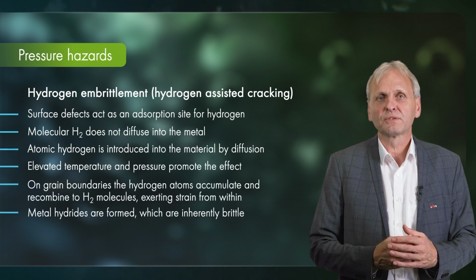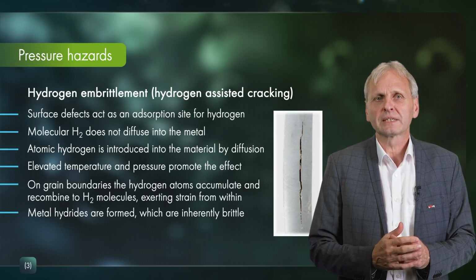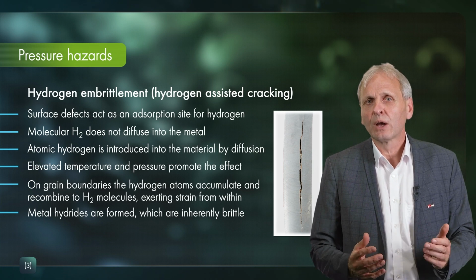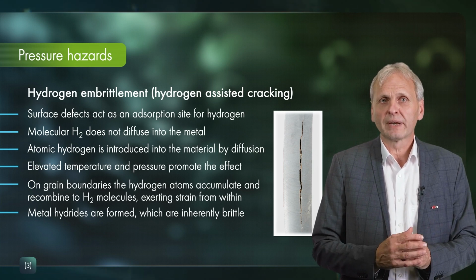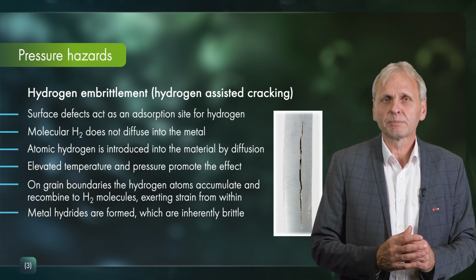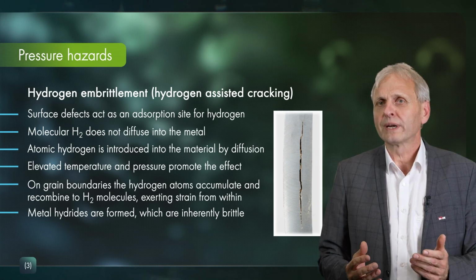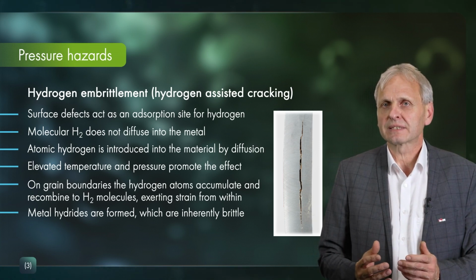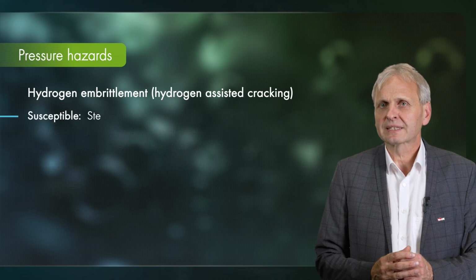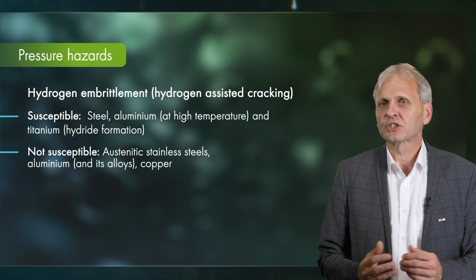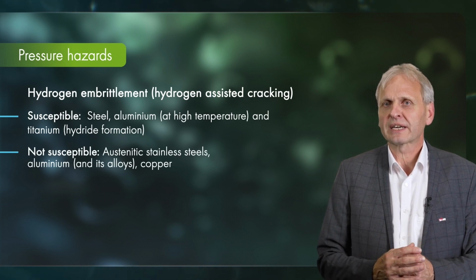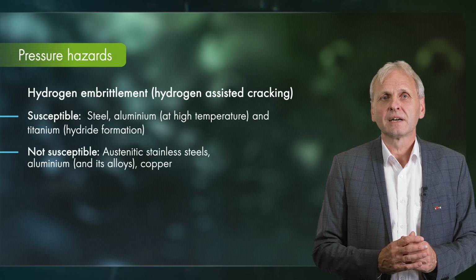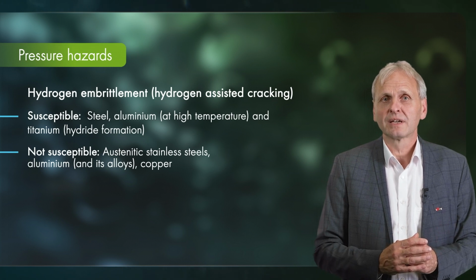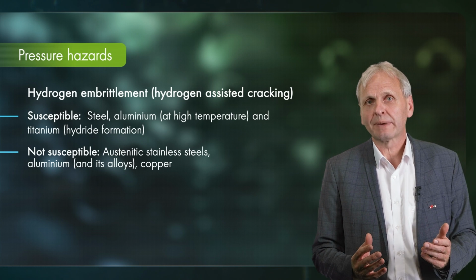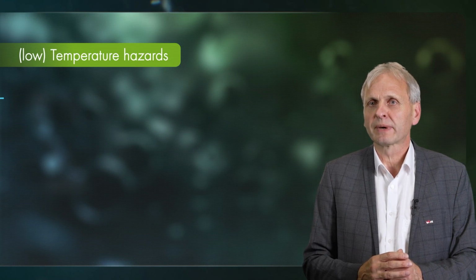Once the hydrogen atoms have diffused into the material, they accumulate at the grain boundaries of the metallic microstructure, where they eventually either recombine to form H2, exerting stress from within by forming gas bubbles in the material, or the atoms react chemically to form hydride species. The microscopic cracks and newly formed hydrides weaken the overall structural integrity, creating a risk of cracking or fracture. Austenitic stainless steels, aluminum and aluminum alloys, and copper are not susceptible to hydrogen embrittlement due to their microstructural composition. This highlights the importance of material selection for hydrogen-containing equipment and machinery.